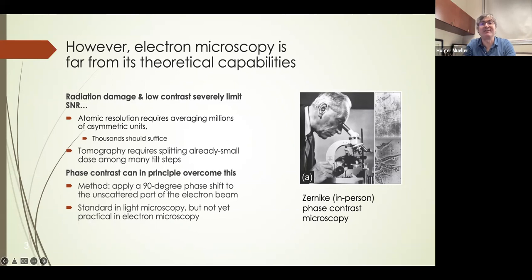In the focal plane of the objective lens, there is a Fourier transform of the specimen. That's true for electron microscopes and for light microscopes. And at the center of this Fourier transform, you see one bright spot that is an image of the electron source. If you're able to phase shift this one bright spot by 90 degrees relative to the rest of the diffraction pattern, then you generate optimal conversion of weak phase modulations into amplitude contrast. So phase contrast is a way to, in principle, extract all the information that is contained in the exit wave after a weak phase object into visible image contrast. Okay.